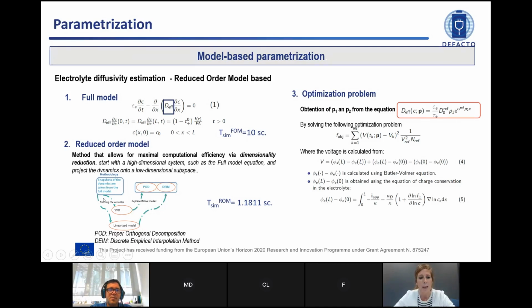So in the preprocess stage, what we need to run is many simulations to get these snapshots and generate a database. And then with this database, we implement singular value decomposition. We obtain the representative modes, and later we apply POD and linearize with these methods. By doing this, we can reduce the computational cost from 10 seconds to only 1 second to solve exactly the same equation and to have exactly the same profiles of the concentration gradients.